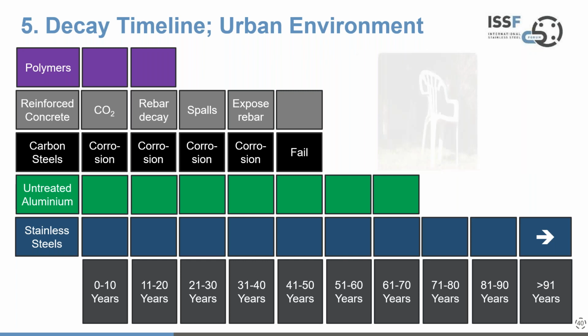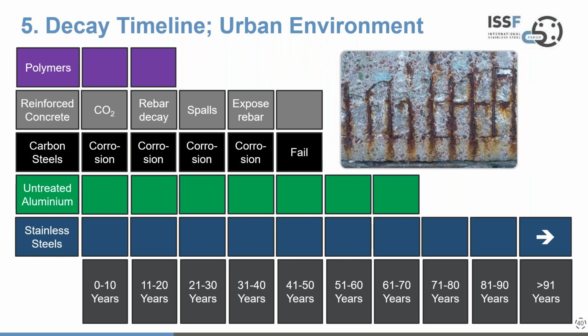When you move to reinforced concrete, then we've touched on how this occurs, but basically the mechanism in an urban environment, you get carbonation of the concrete that reduces the pH of the concrete that causes the rebar to decay. It's a volume expansion because rust is bigger than the substrate material. That causes the concrete to spall and crack. That exposes the rebar and the corrosion continues. So reinforced concrete, if it's not made with either a properly coated rebar steel product or stainless steel, will suffer this process. And you've probably got somewhere between 40 and 50 years of life here.